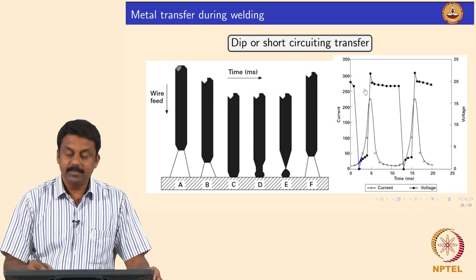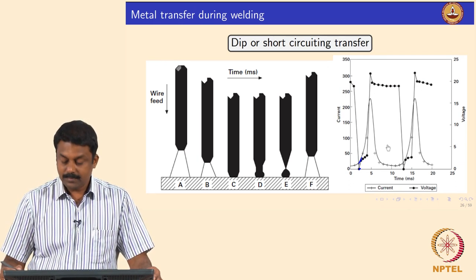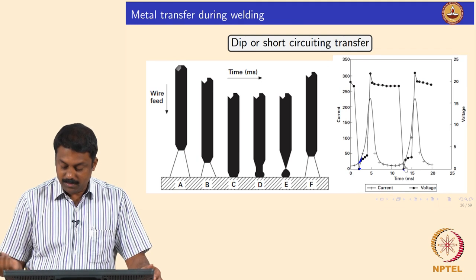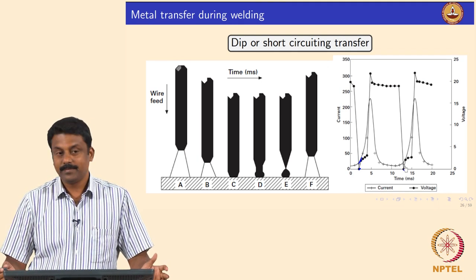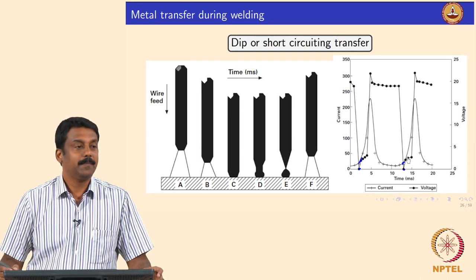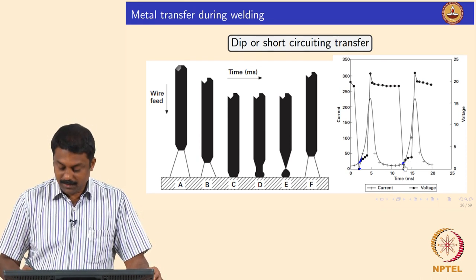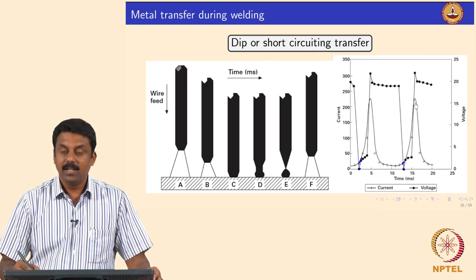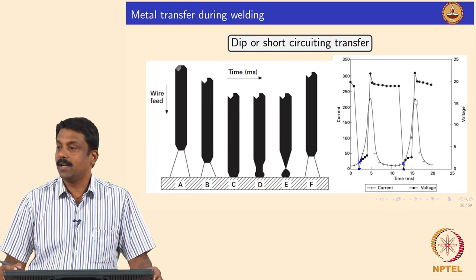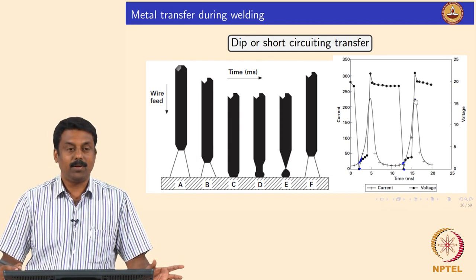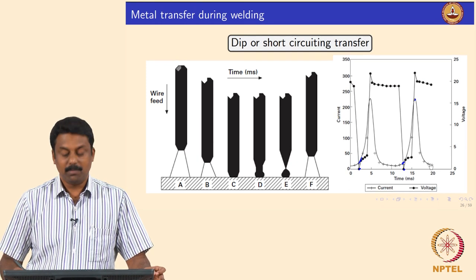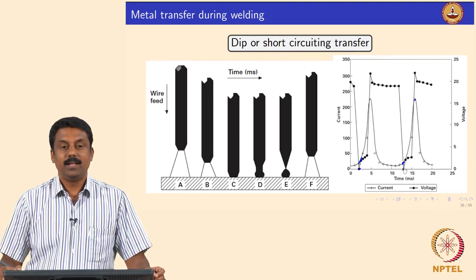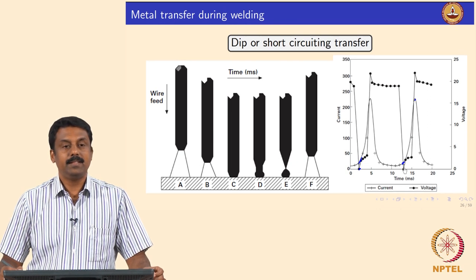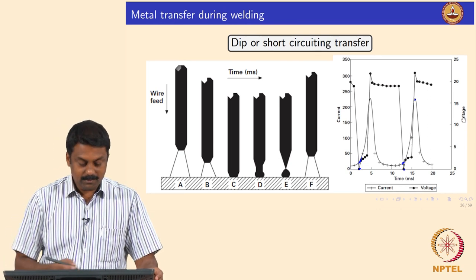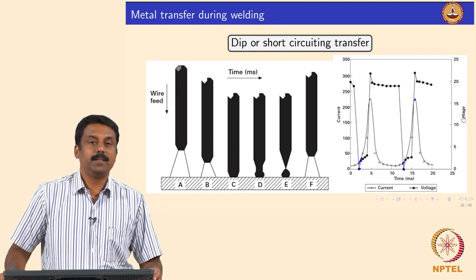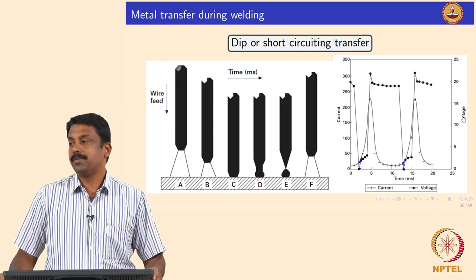So this is the arcing voltage, okay, and the arcing current, and then the moment short circuiting is established, the voltage becomes 0. So the current becomes minimum, right? And then you continue again, so this is the arcing voltage, and during this process you give a current pulse to melt the droplet and then bring it down. The moment the voltage becomes 0, short circuiting, minimize the arc, right? It is clear. So this is how the controlled dip short circuiting transfer is established.